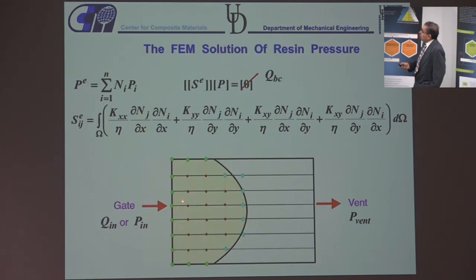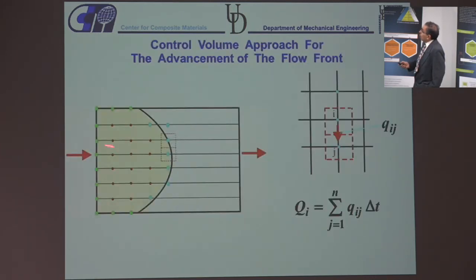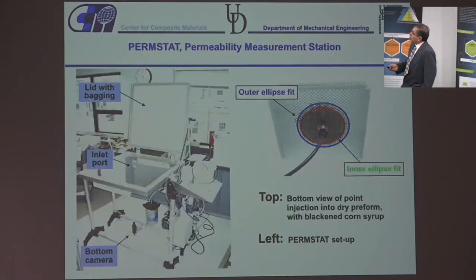Once I know the pressure, I associate a fill factor with each node, and I update the fill factor. So initially, wherever there is resin, the fill factor is 1. Wherever there is no resin, the fill factor is 0. Once I find the pressure, I can calculate the flow rate that goes from one element to the next element, and I can update the fill factor. So at the next time step, my domain has changed because the fill factor that was 0 or less than 1 has become 1. And so that way I can update my filling domain. So that's how we solve the problem.